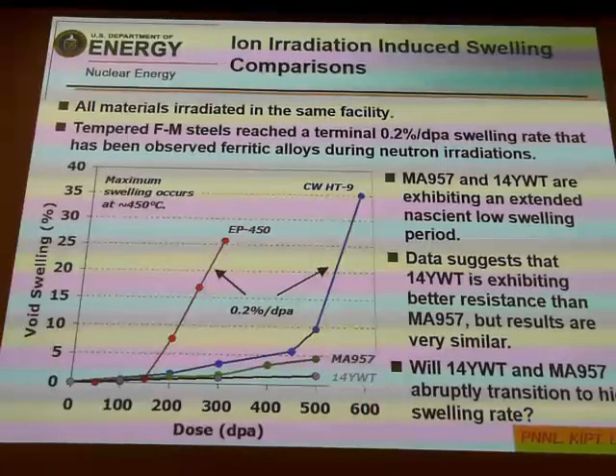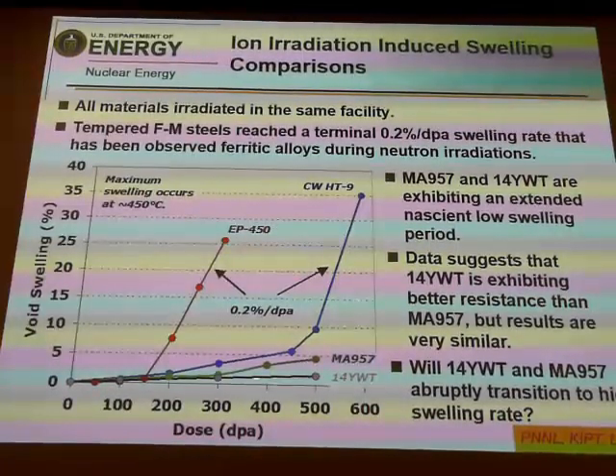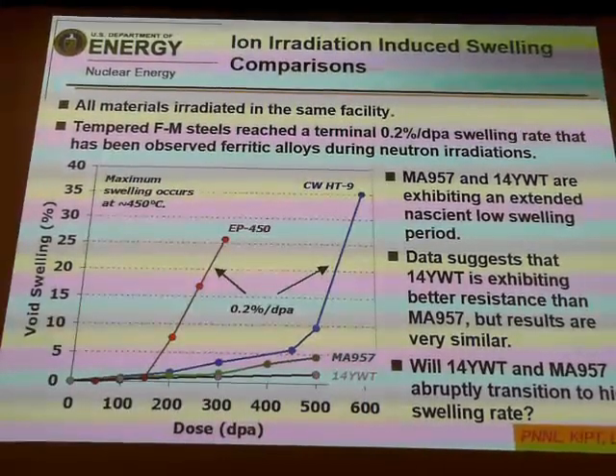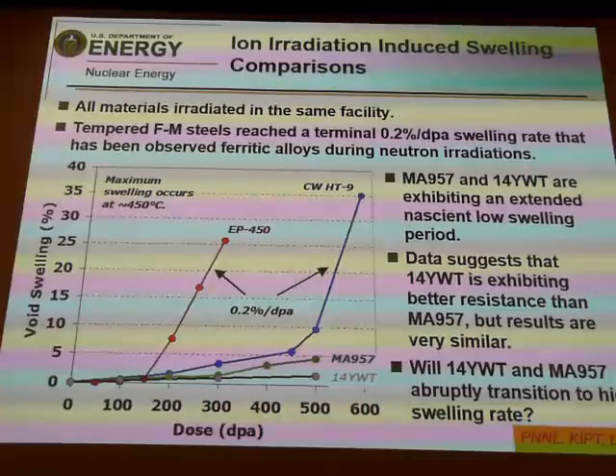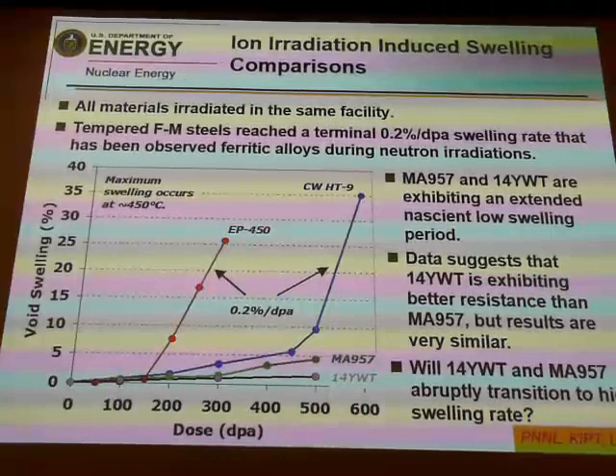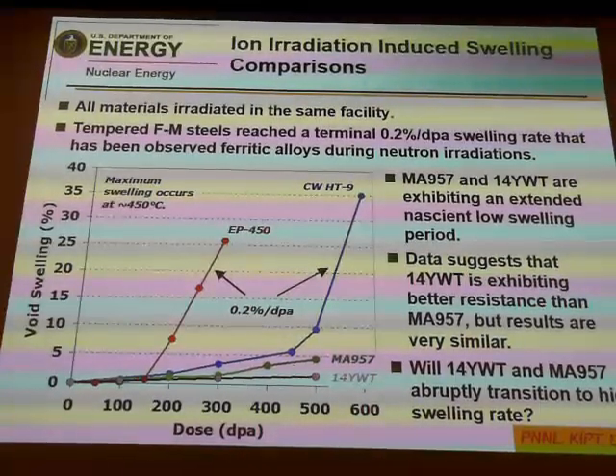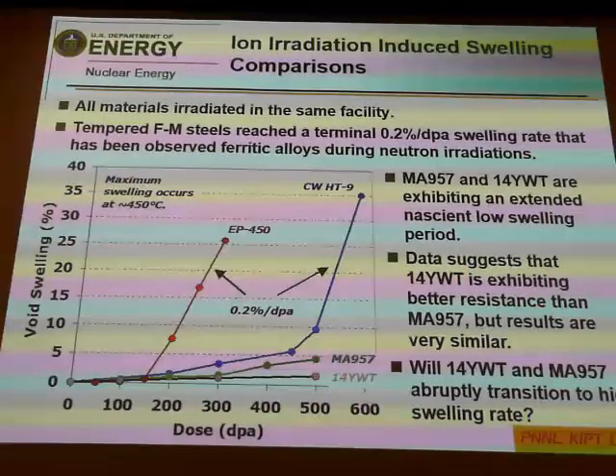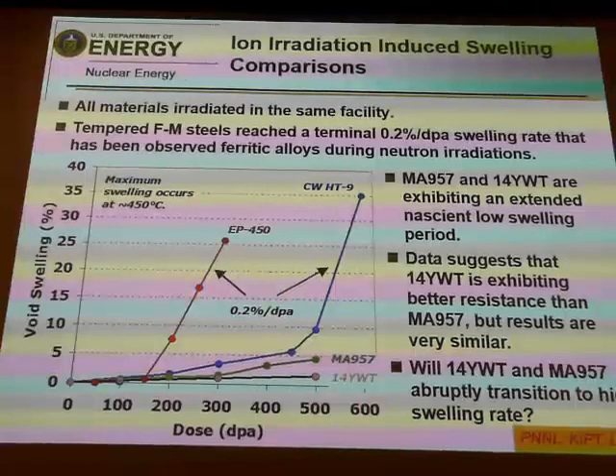Well, what happens when you have a refractory period like that, where you said you're recycling some old materials that sit on the shelf for years? Does that affect the results at all? As long as when you shut the reactor down, you keep it at a low temperature and you don't heat it back up to a temperature near the radiation temperature, which is where you anneal out some of these defects. We've done other irradiations where we shut it down. As long as it stays cool, those defects don't go anywhere. You heat it back up to that reactor temperature and continue, and you can get the equivalent to a long-term irradiation at that temperature.